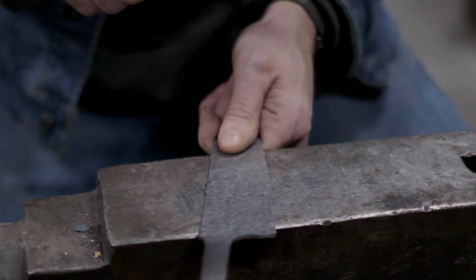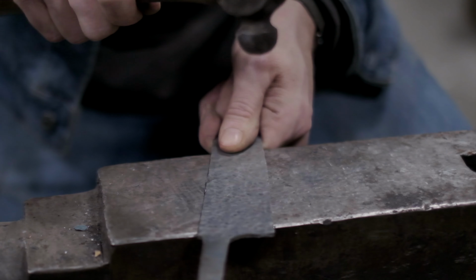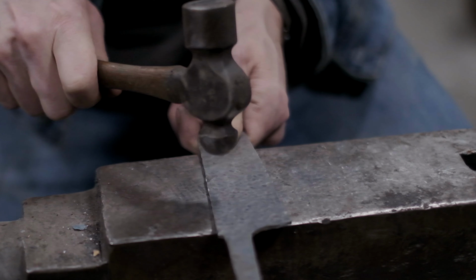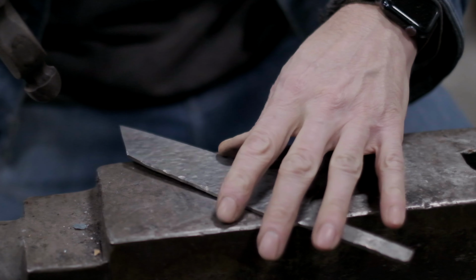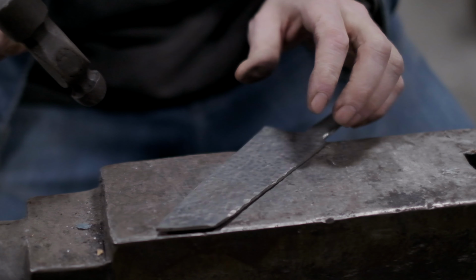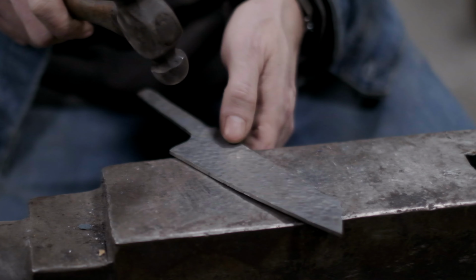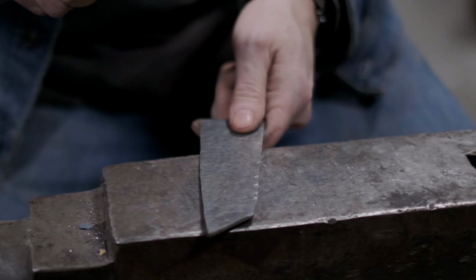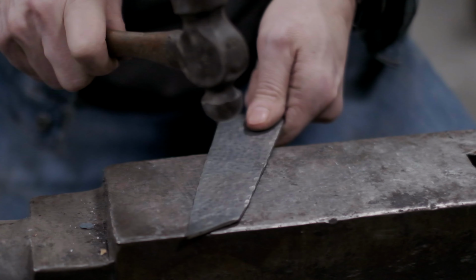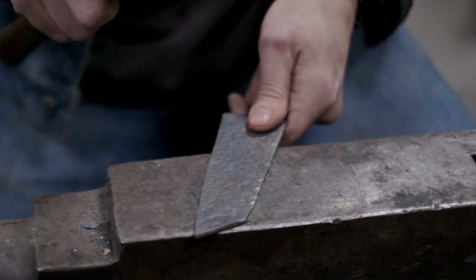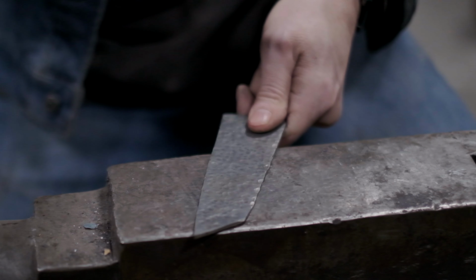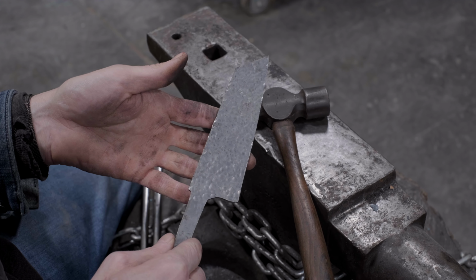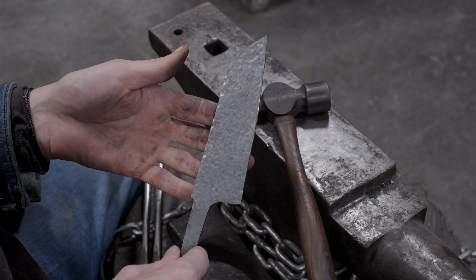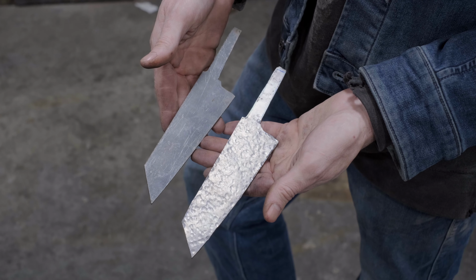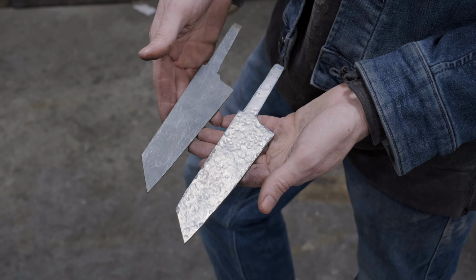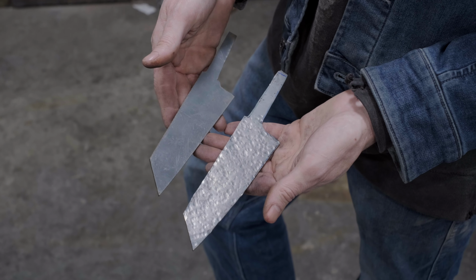Instead of the usual hot forging required to pattern Damascus, I'm going to try something new, cold embossing the steel. Using nothing more than an old ball peen and the anvil, I hammer both sides of the blade evenly to disrupt the layers of the steel. So now we have two identical blades, one with this embossed texture that's going to give a really nice random pattern, and the other is just going to display the straight layers of the steel. So the next step is heat treatment.